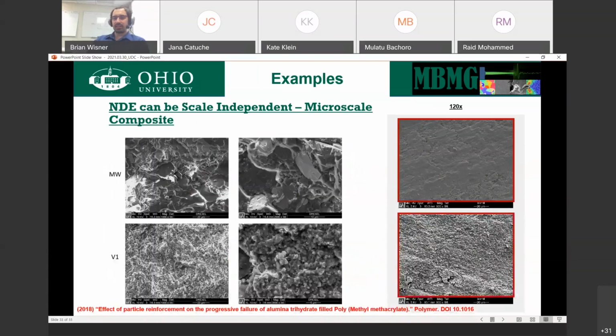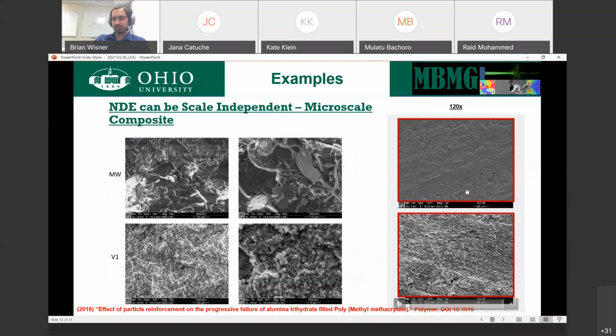And just to show you exactly what's happening, this is what you see here. As you step through it, through the fractures, you barely even see the fractures here. They're all extremely small. What that means is the way this material is set up, the way it was developed, is that instead of having a single crack that grows across the whole thing, the particles that are placed in here are of a size that actually impedes growth. It grows to a certain size and stops, and another location nucleates. As a result, we get a much better elongation behavior.